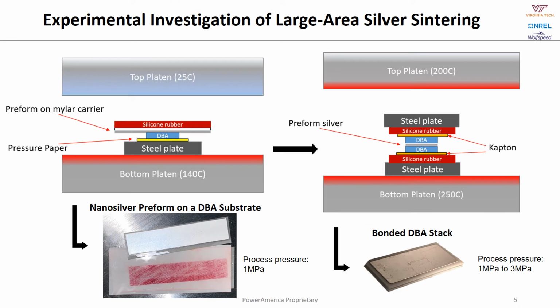In order to maximize the reliability of the substrate stacks that we're investigating, first we need to optimize the process that's being used to actually bond the substrates together. We use a large area silver sintering process that is fairly low pressure, 1 to 3 megapascals during the actual sintering step, and uses a sintering temperature of about 250 degrees centigrade.